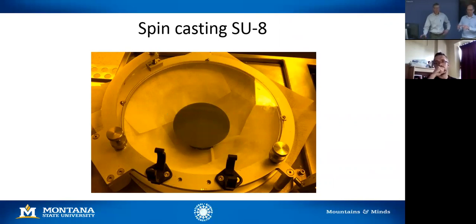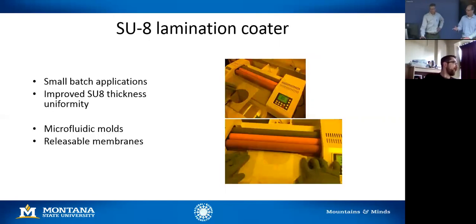And so the thicker, more viscous films, we have a hard time getting a uniform coating with spin casting. For example, a user does films 25 micron thickness. For instance, we'll see plus or minus 5 micron variation, so significant variation. And if we go to these pre-made laminate sheets of material, thickness variation is 5%. So we're talking 1 to 2 micron variation in thickness. And in these pictures, it's really impossible to see the actual laminate sheet because they're basically discs of this material that are appropriately sized for the substrate. I see.